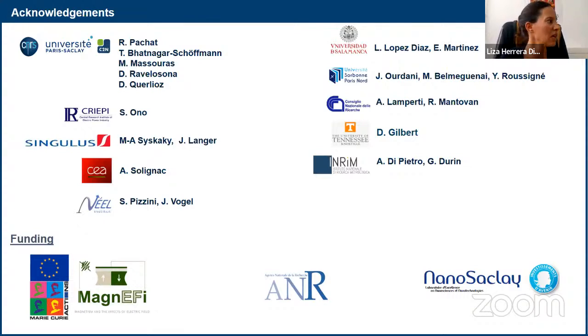So it's actually funny because for us, you can see very clearly that, for example, in the experiments where we annealed samples, if you take the annealed sample out of the oven and you try to do electric field, it doesn't really work that well, because it comes from the oven, so all the water is out. But then if you leave it sitting in air for a few days, then it will be very efficient. And I know from other labs as well that there's this sort of black magic on the devices that sometimes you blow on it and it works better because you just got hydrated. So it's not just the oxygen in the hafnium oxide that will do everything for you. Yeah. Thank you very much.